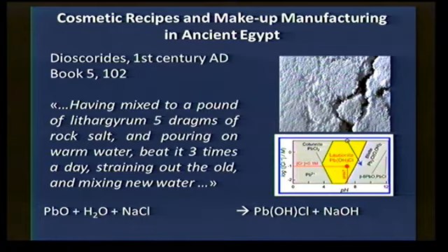So we did a number of simulations in the lab in order to understand this recipe and other recipes, and in order to compare our results with archaeological makeups. And if you don't replace the water in a regular way, then because you have production of sodium hydroxide, your solution becomes very alkaline. You have a shift of what we call the pH. And then instead of producing this particular chloride, this is the phase diagram, you can precipitate something completely different.